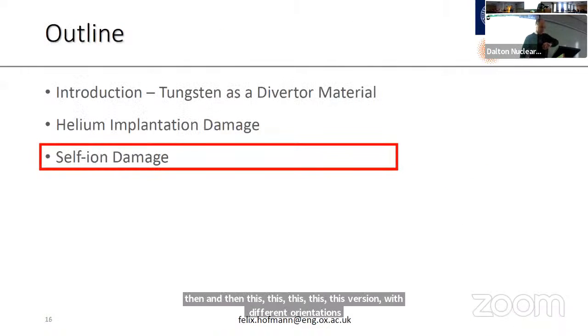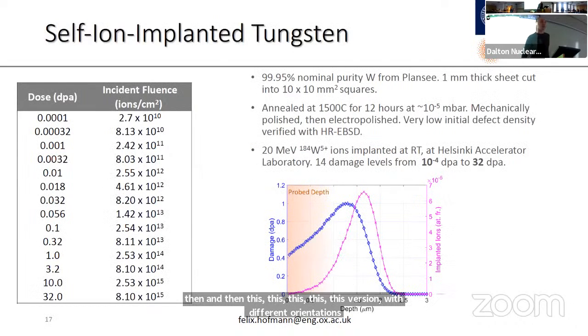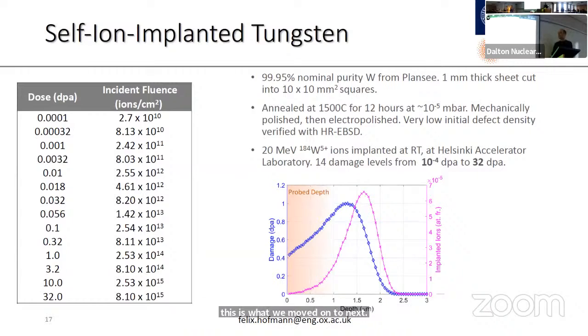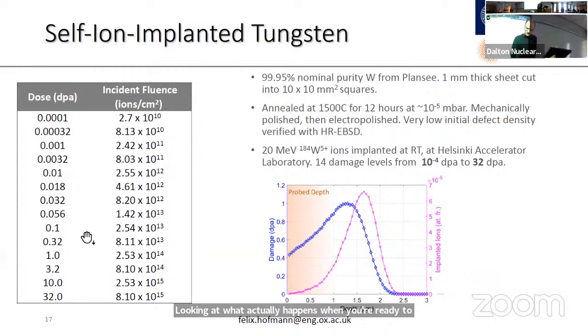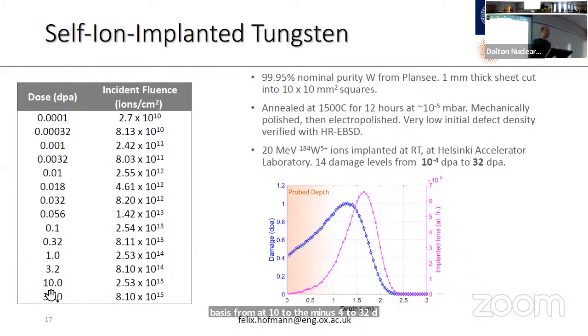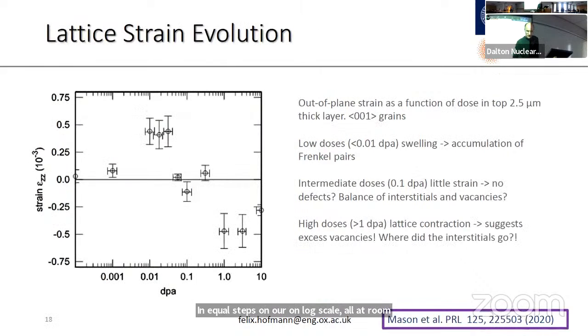All right, I'll zoom through self-ion damage, because this is what we moved on to next, looking at what actually happens when you irradiate with self-ions. Here I'm going to be talking about this set of samples we made: tungsten irradiated to doses from about 10^-4 to 32 dpa in equal steps on a log scale, all at room temperature. The idea really was to try and understand what's going on.